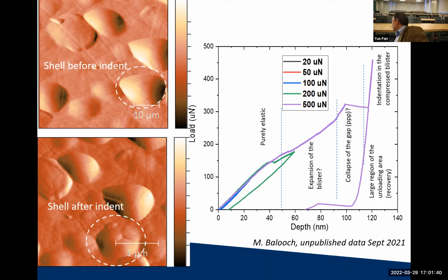And then when we look at the stress strain curve, which is interesting, if you go to low loads, you can actually repeat it a few times, relatively often. Let's just poke it with a very low load. But at some point, you hit the point of no return. So we load it, hit the point of no return, unload, reload, and then you increase. This is pure elastic because it comes back a few times, but then it changes slope. So there's some plasticity. You have the expansion of this in a lateral way.